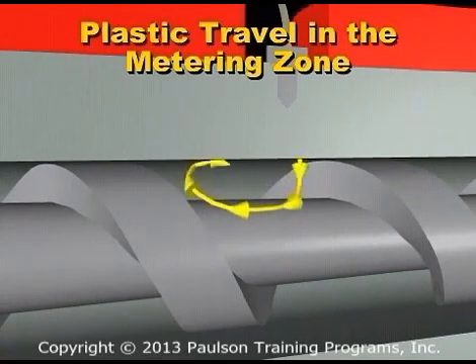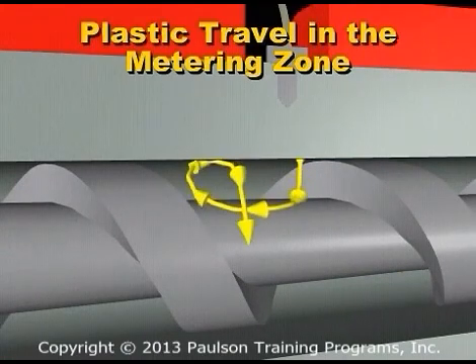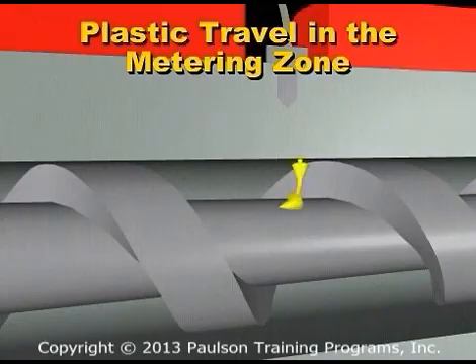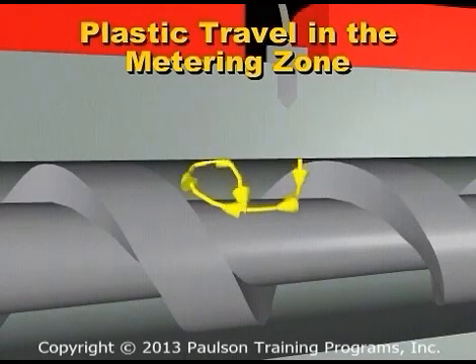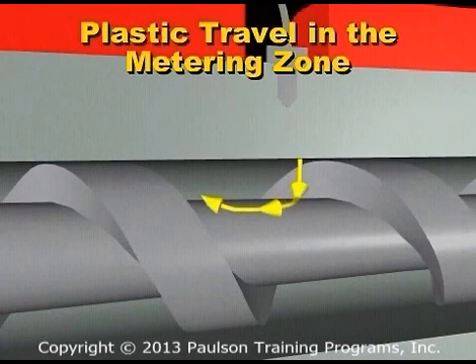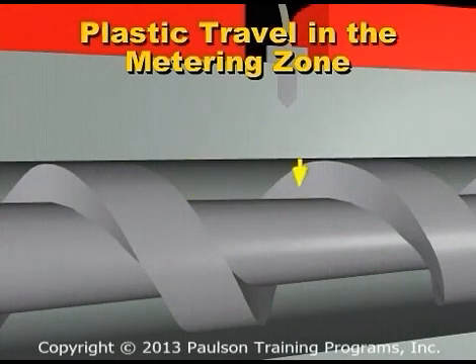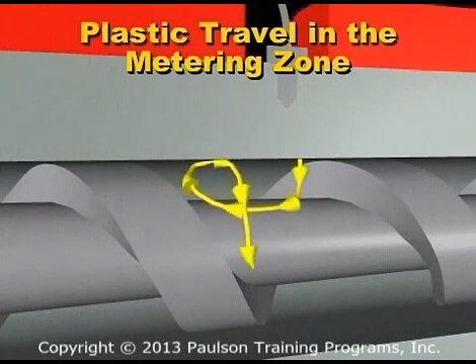The plastic near the surface of the barrel is turned downward by the pushing edge of the screw flight. The plastic then crosses the screw channel where the trailing edge of the flight pushes the plastic back up to the barrel surface. This constant motion of the plastic as the screw rotates shears and mixes the melt.